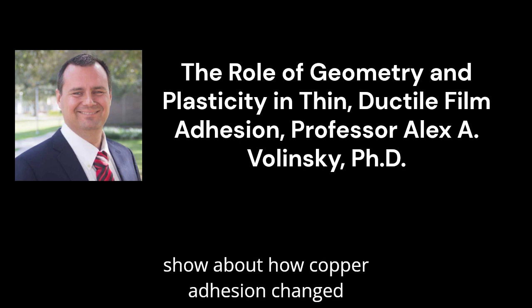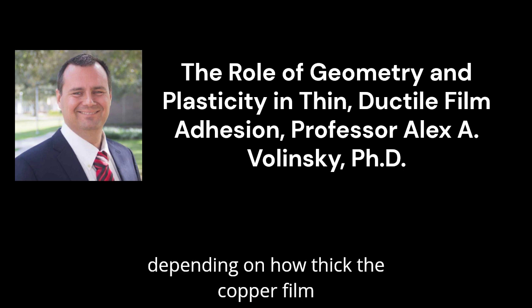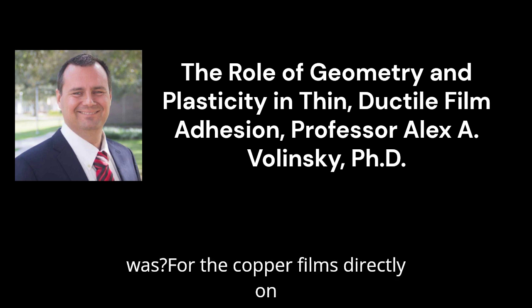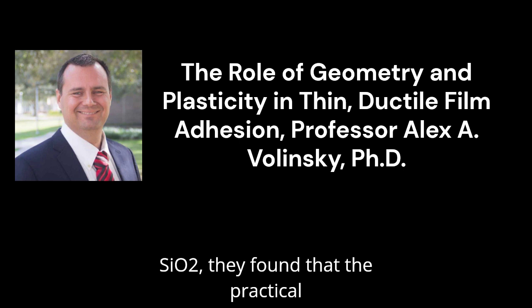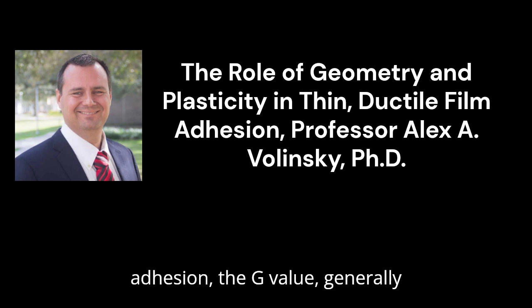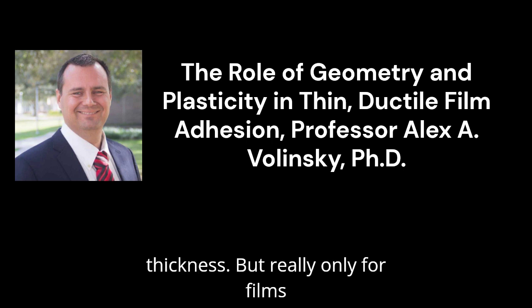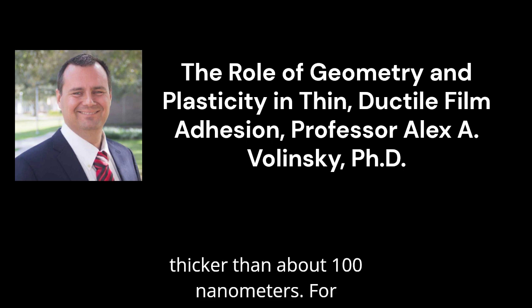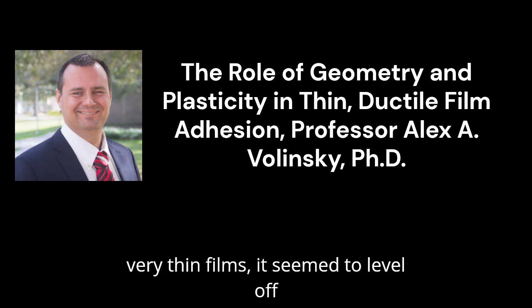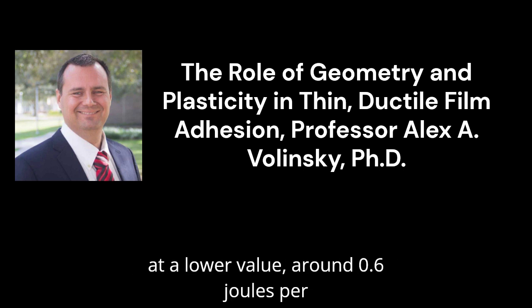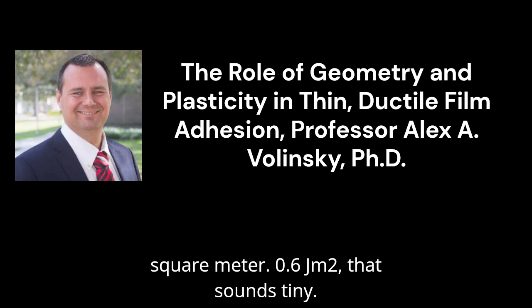What did the test show about how copper adhesion changed depending on how thick the copper film was? For the copper films directly on SiO2, they found that the practical adhesion, the G value, generally increased significantly with film thickness. Okay. But really only for films thicker than about 100 nanometers. For very thin films, it seemed to level off at a lower value, around 0.6 joules per square meter. 0.6 J/m², that sounds tiny.